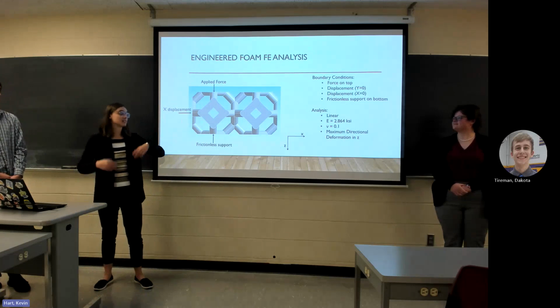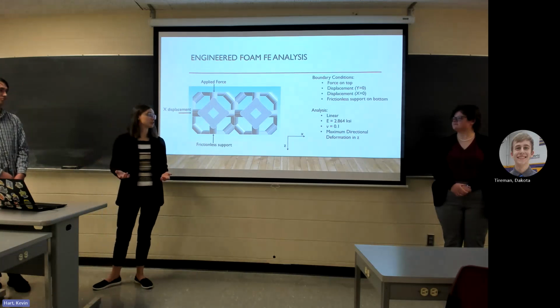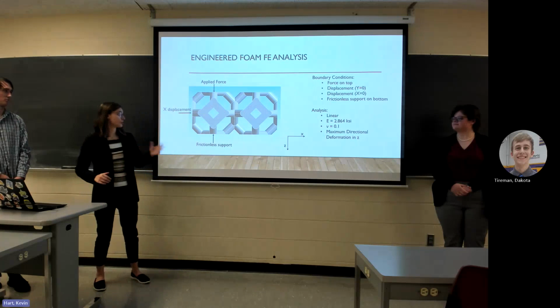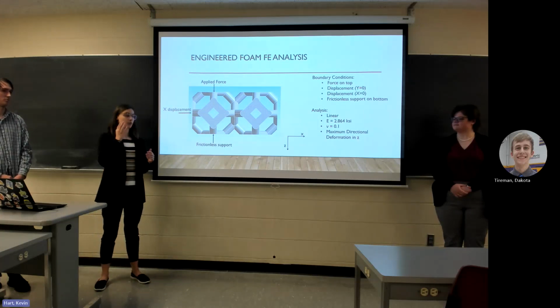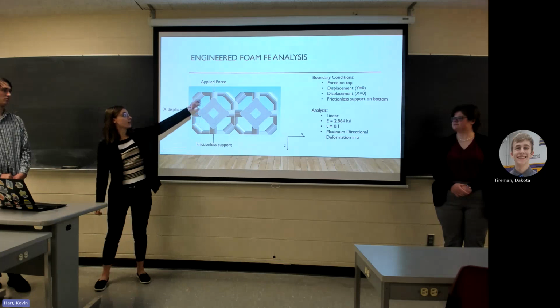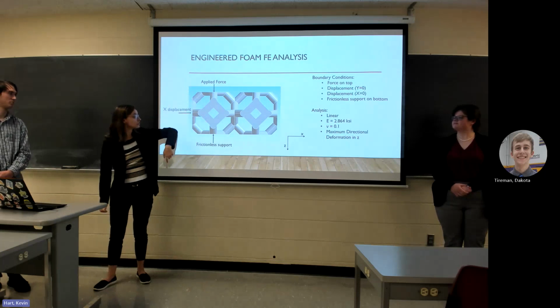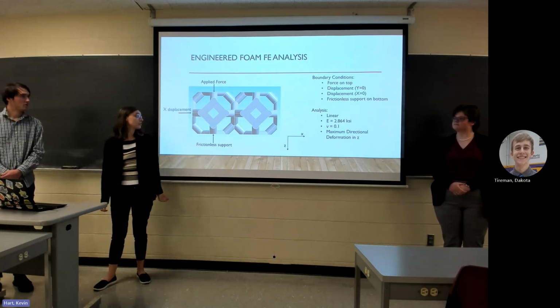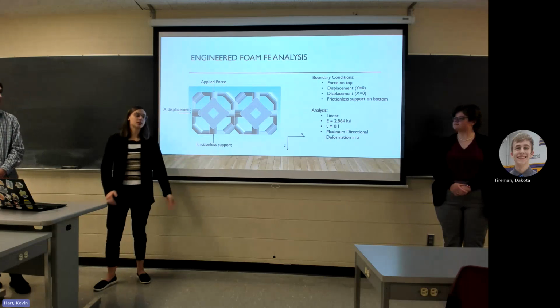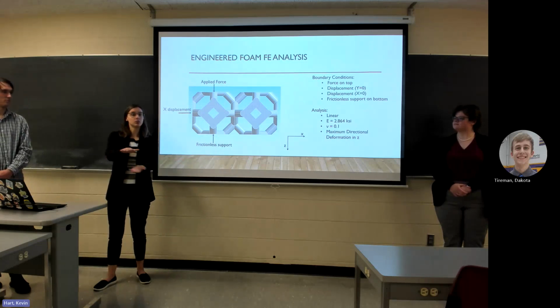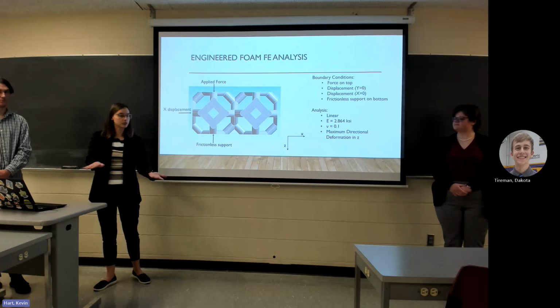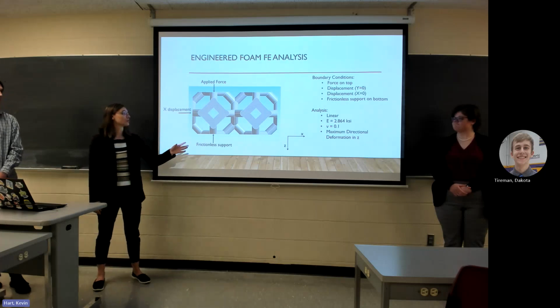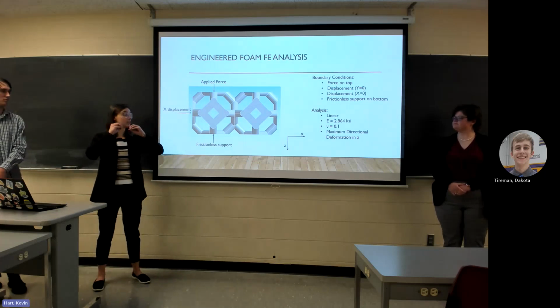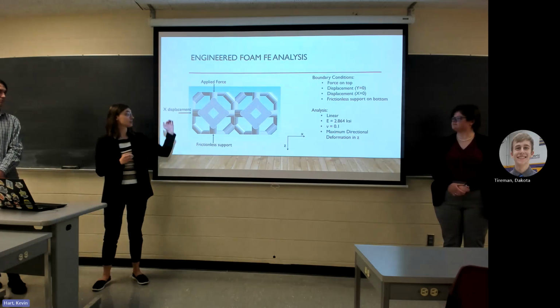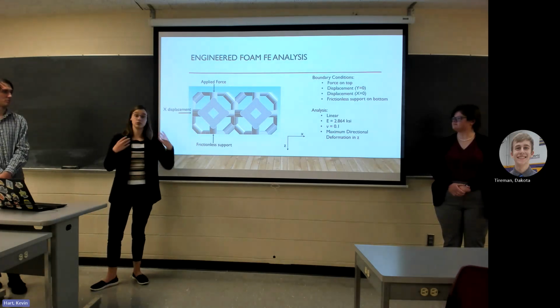So in order to do that, we had to mimic the compression test machine. So in order to do that, we had to do 4 types of boundary conditions. So we had the applied force going down in the Z direction. We had a frictionless support on the bottom of it, because that's how the plate is on the compression test. It's not a fully fixed support, it's frictionless. And then in order for the foam to squish properly in ANSYS, you have to have an X displacement and a Y displacement that are both equal to 0.